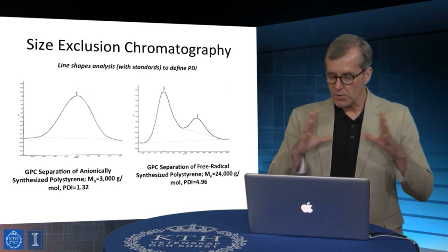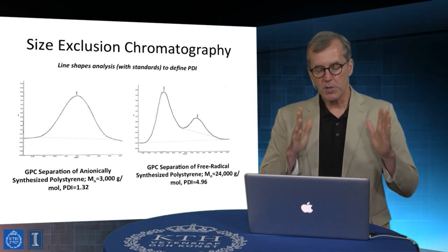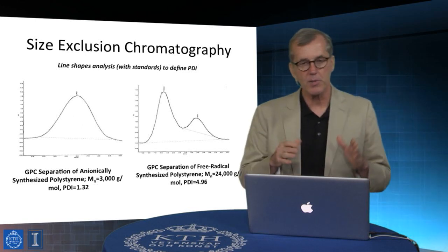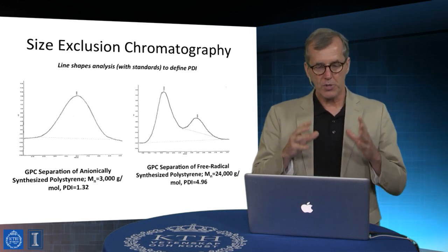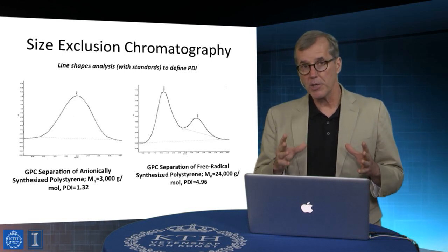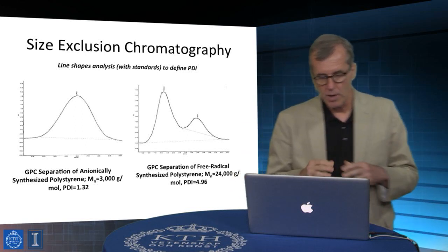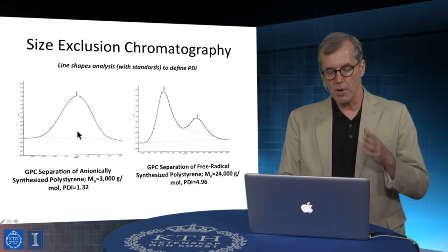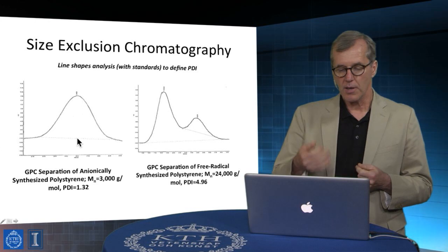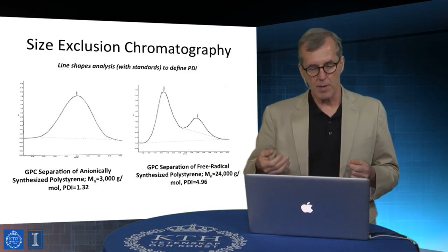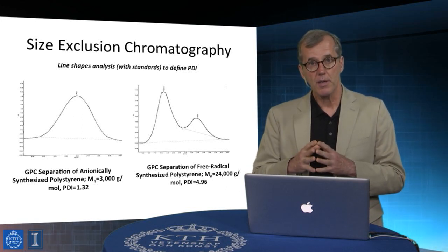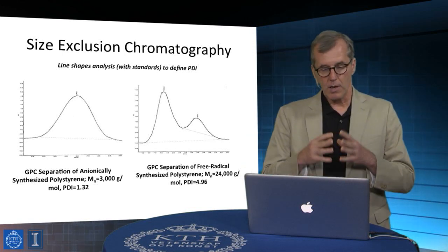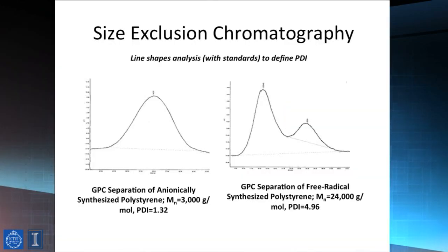And finally, I'll say that there's one other component in it, right? And that is we not only look at what the elution profile looks like, these times, how long a thing stays on the column, which is saying something about time, but we also look at the line shape of the component eluted from the column. So, for example, the line shape is one that reflects not only how long a sample has spent on the column, but it also reports on the polydispersity of that sample. So, for example, if I have a polystyrene, such as shown here, with a particular molecular weight, the elution of that from a calibrated column is going to be characterized by an explicit line shape that's unique to that experimental circumstance.